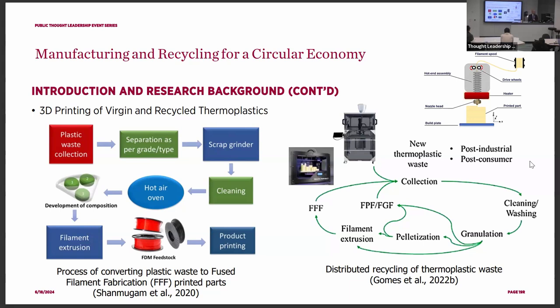In a different way, on the right-hand side is fused granular fabrication, the FGF process. In this process, we don't use filament; we use pellets. You can see the waste material goes through collection, cleaning, washing, and granulation. We can use a machine to crush it into small pieces of flakes or pellets, and then directly use the FGF process to do the printing. The pelletization and filament extrusion we just get rid of, so we save at least one heat cycle.